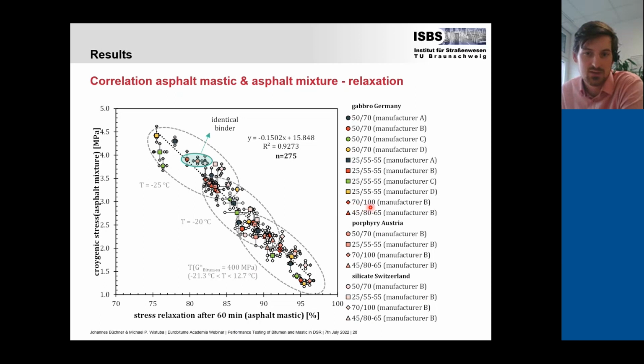So the softest binder here was the 70/100, which was tested with the gabbro, the porphyry, and the silicate. And all of those are, for each of the temperatures, in the good performing area, performing better than the others. Cryogenic stress is lower as expected, and stress relaxation is higher as expected. So a clear differentiation based on the binder, and since we did not test the binder alone, also the influence of the filler, which is already included here, and which shows clearly this correlation between mastic behavior influencing the low temperature performance of the mixture.